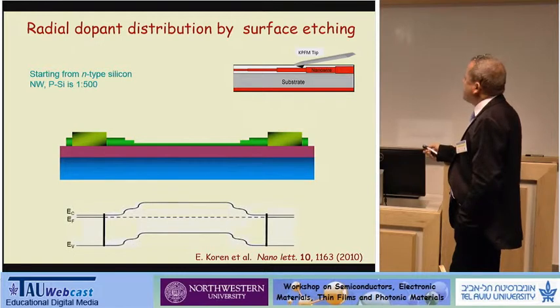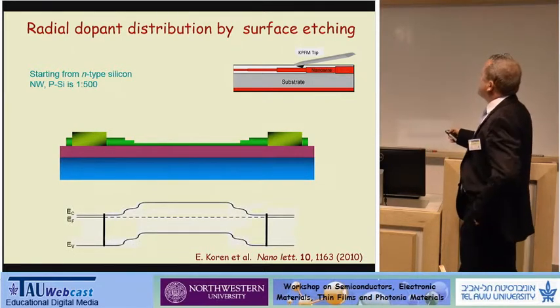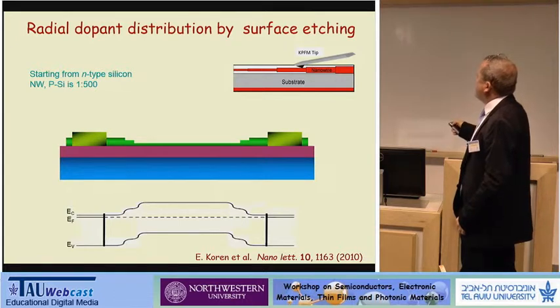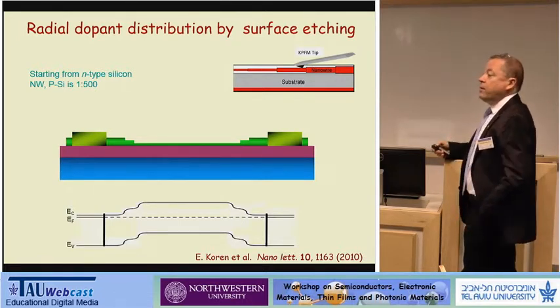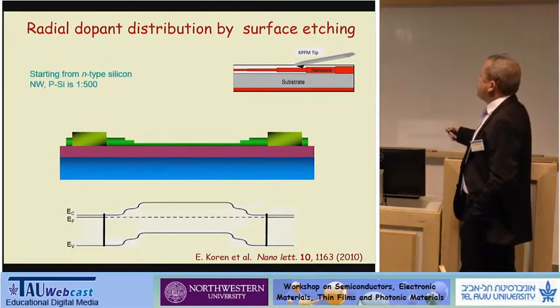It looks very simple on the slide. It takes some time to do this in a careful way. Basically, when you form this structure, when you form these steps, you come with a KPFM tip and measure these steps, measure the potential distribution along these steps.